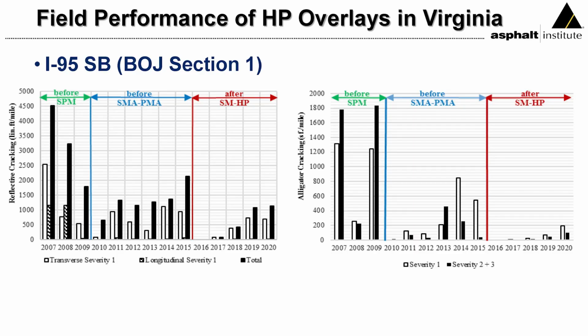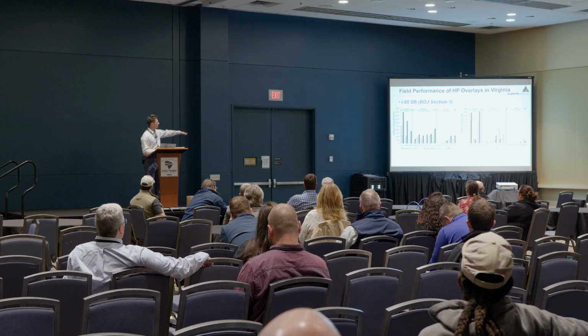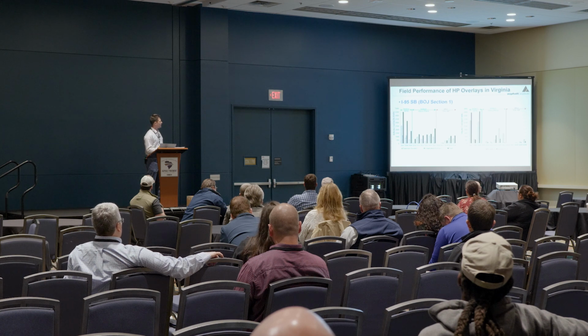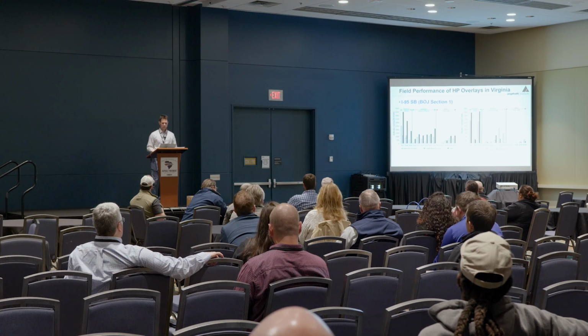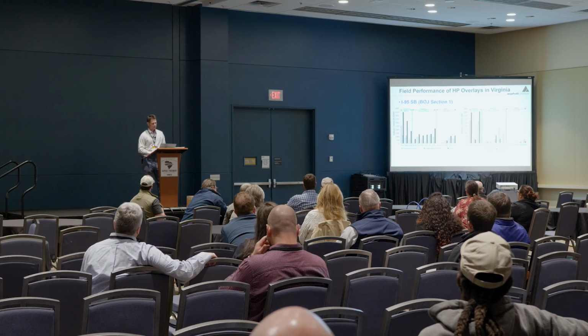Now, they also measured alligator cracking, which is bottom-up fatigue cracking, as well as reflective cracking. And again, reflective cracking is one of the types of cracking that this technology has really found a home and has really shown success. And you can see in this data the rate at which the reflective cracks are occurring with that SMA compared to the high polymer. Now, I only have data here going through 2020, but again, very encouraging.